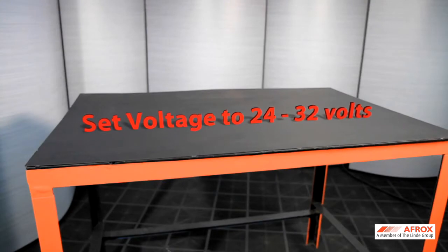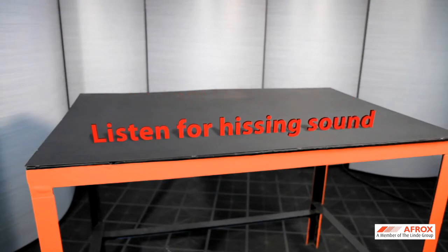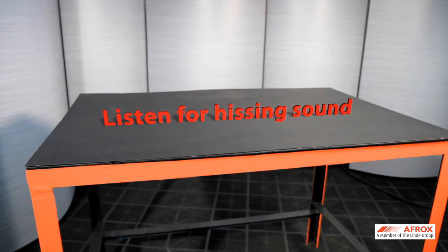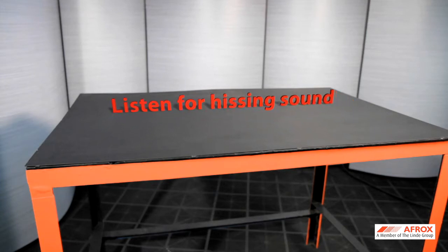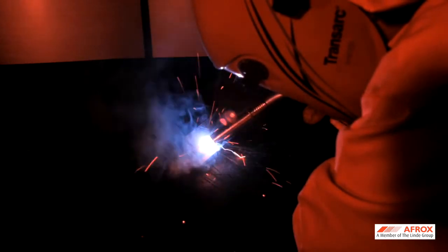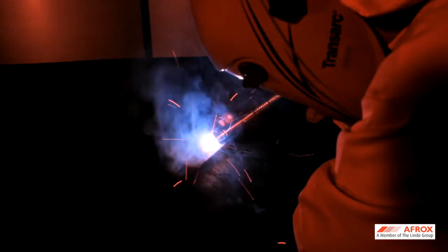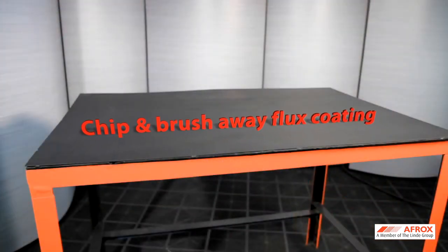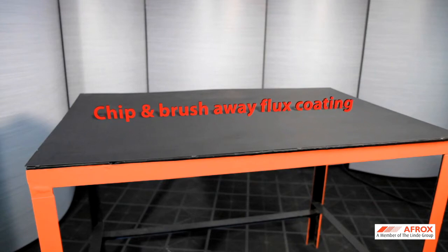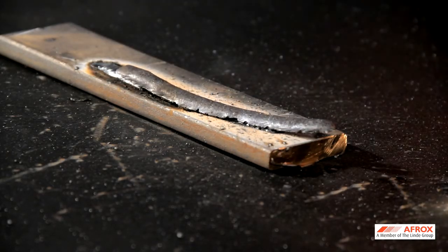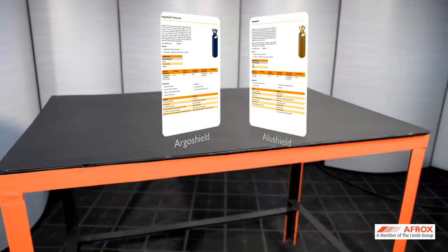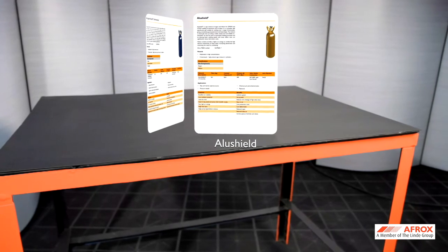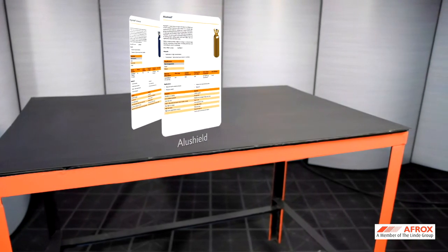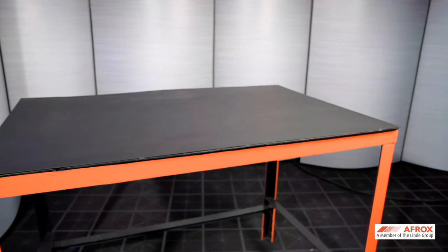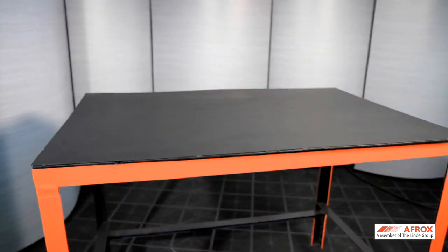The voltage on the power source is set between 24 and 32 volts. The wire feed speed is set until you hear a hissing sound with very little visible spatter. Flux cored wires leave a flux coating after welding and must be chipped and brushed away before welding a second weld, the same as with shielded metal arc welding. Select the correct shielding gas for the wire selected, for example, Argo Shield for mild steel and Alu Shield for aluminium.